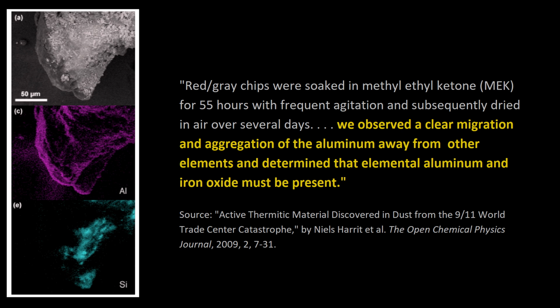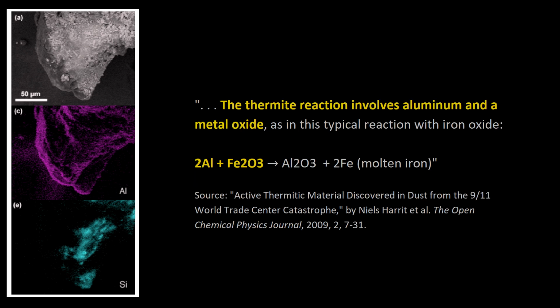They write that, quote, red-gray chips were soaked in MEK for 55 hours with frequent agitation and subsequently dried in air over several days. We observed a clear migration and aggregation of the aluminum away from other elements and determined that elemental aluminum and iron oxide must be present. The thermite reaction involves aluminum and a metal oxide, as in this typical reaction with iron oxide. 2Al plus Fe2O3 yields Al2O3 plus 2Fe, molten iron, end quote.